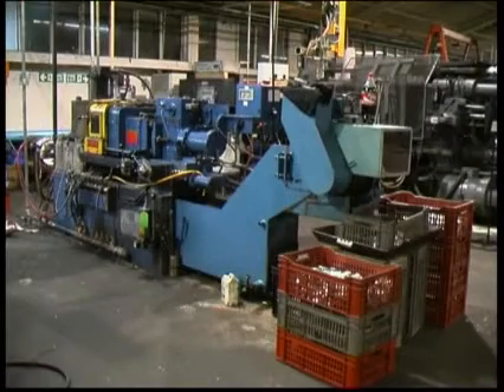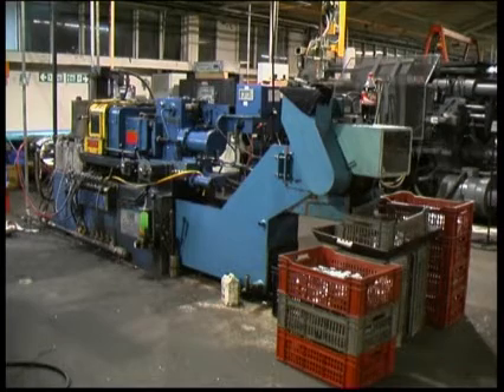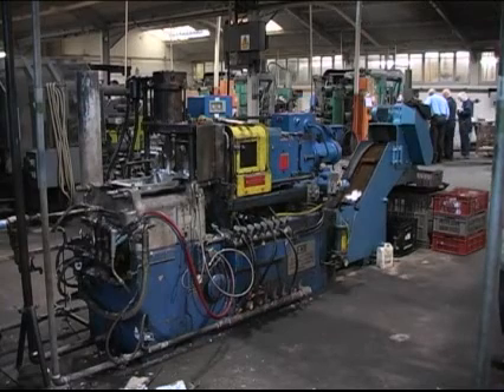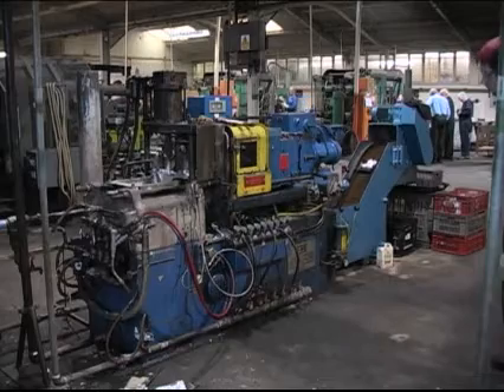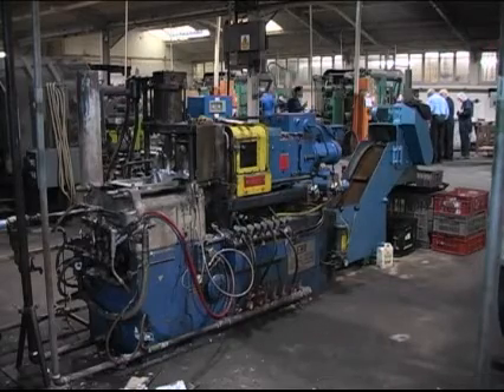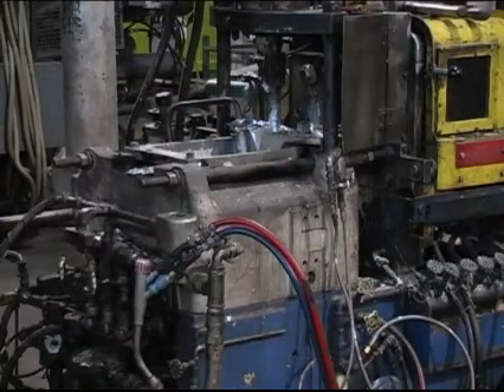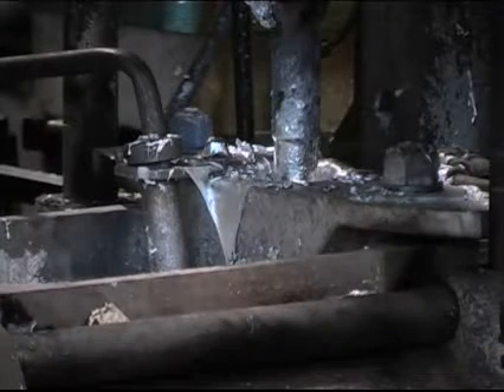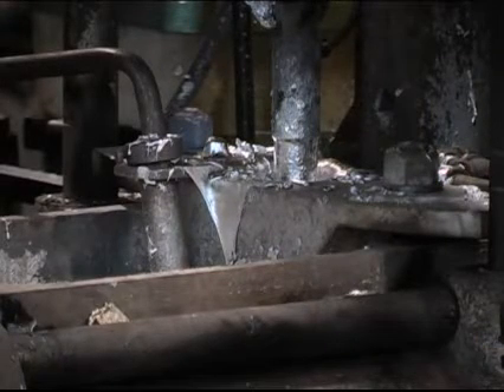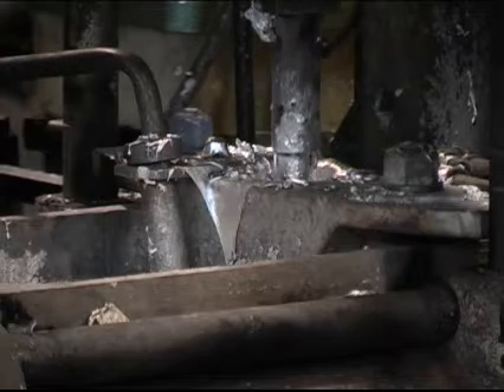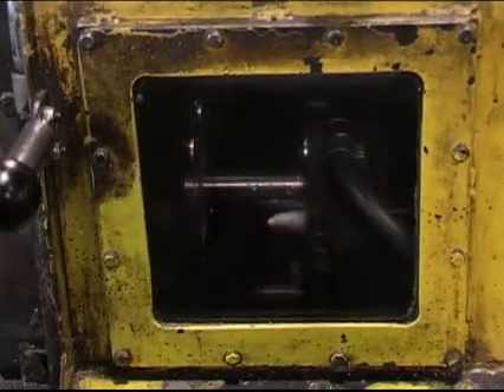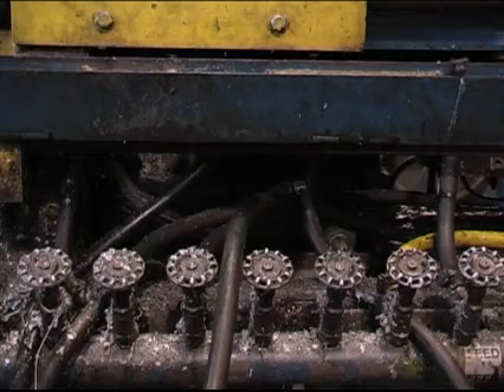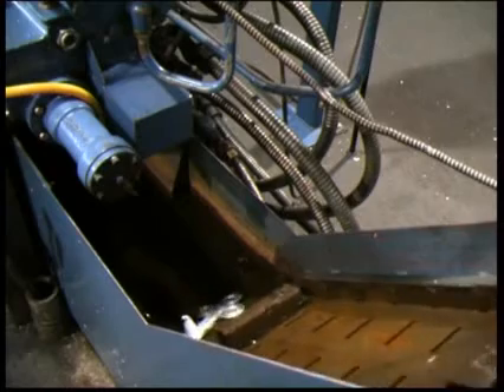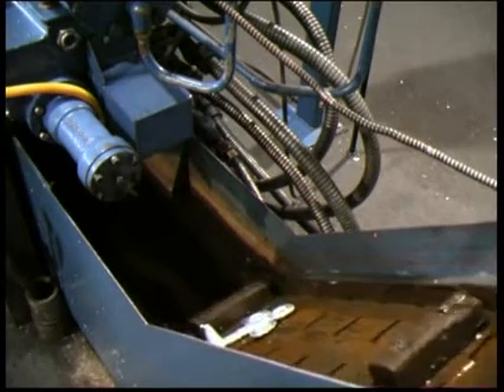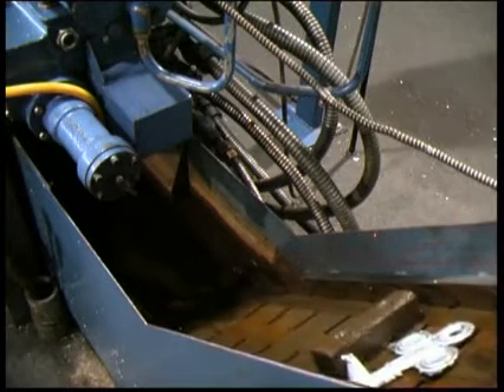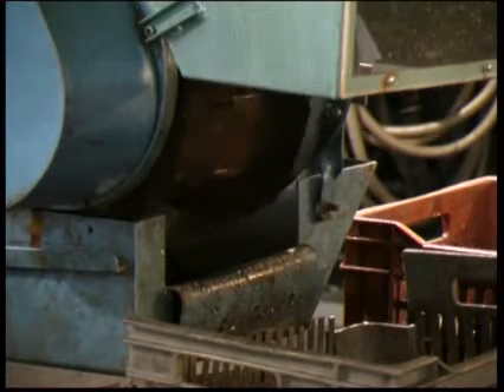This automatic pressure die casting machine is being used to produce inner seals for a gearbox. Molten zinc is held in a heated crucible at one end of the machine. The molten zinc is then forced from the crucible by a ram into a two-part die. The die is then pulled apart and the ejector pins push the component out of the die into the cooling reservoir below. A moving conveyor belt collects the casting and transports it to the component basket for the operator to check.